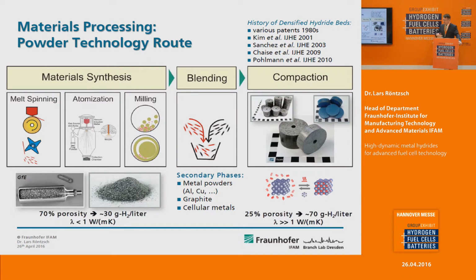And you could already at this stage use the powder to hydrogenate it, forming a hydride, but then you have a very low heat transfer. You can imagine isolated metal particles have only very few contact points and heat transfer is very low. We speak about heat transfer coefficients of 1 watt per meter Kelvin and less, which is not enough for highly dynamic use of metal hydrides.